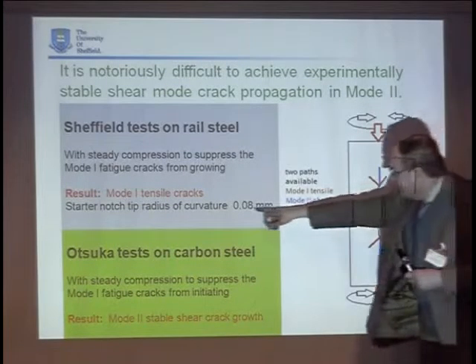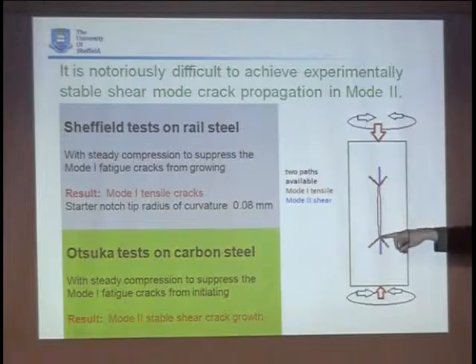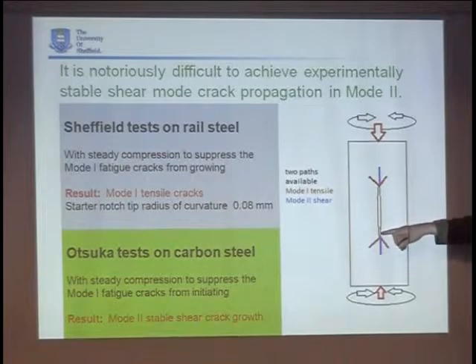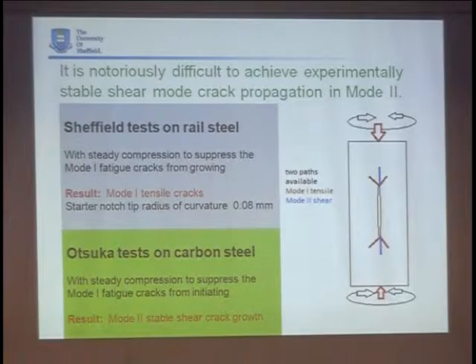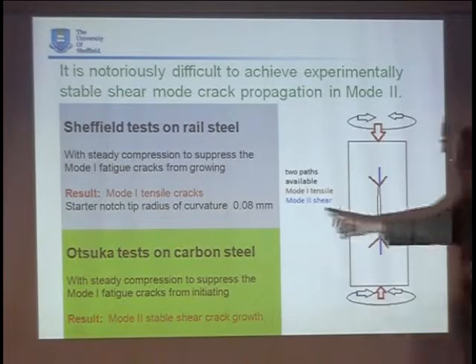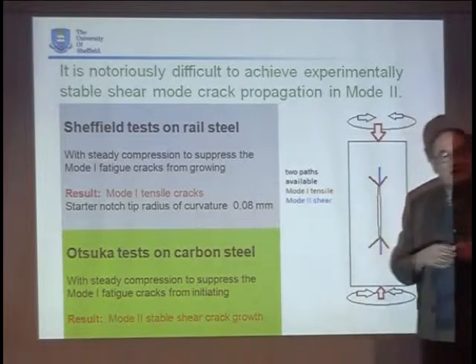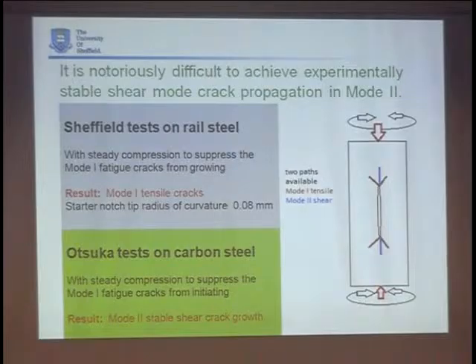Only one other point I ought to mention. We couldn't really pre-crack our samples, couldn't think of a way of doing it. The cracks are put in by spark erosion with a small wire, and so in our case we have a root radius of curvature of 0.08 at the end of the notch, that's what to call it. But Otsuka, I think he pre-cracked his samples, and I guess they were a bit sharper.